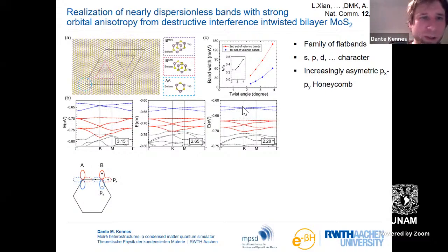Now, what we can do to go beyond that is we can look at that second family of flat bands. So one important note to take here is that we really want these flat bands to detach from the other bands, all the band spaghetti below here, these black bands. And indeed, this does happen. When you go to a small enough twist angle, you now detach this flat band. You really want to think about isolated flat bands. You don't want these to overlap with other dispersive bands, which make your life messy. And again, this looks strange a bit because you have this Dirac cone here in the middle, but then, even on the scale of these flat bands, you have very, very flat bands attached here at the top and, to a lesser degree but still visible, on the bottom here.